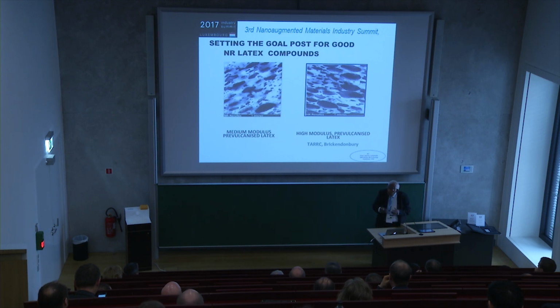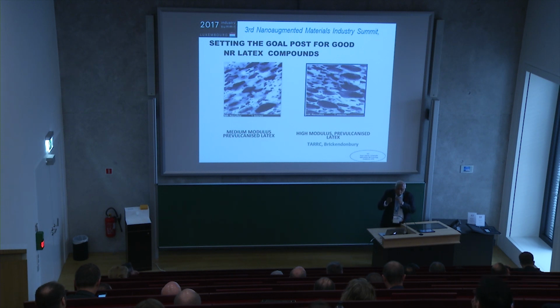It's easier to blow. So this would go into gloves, and the high modulus goes into contraceptives, condoms. It goes into elastic thread. So according to the use, we tailor make it broadly in 3 grades of low modulus, medium modulus, and high modulus. And within this, we tailor make it to specific products. And our challenge is to introduce the CNT into this matrix.